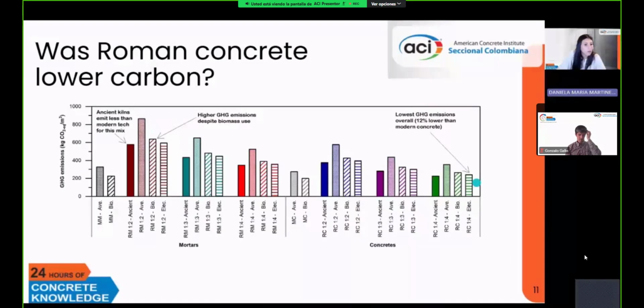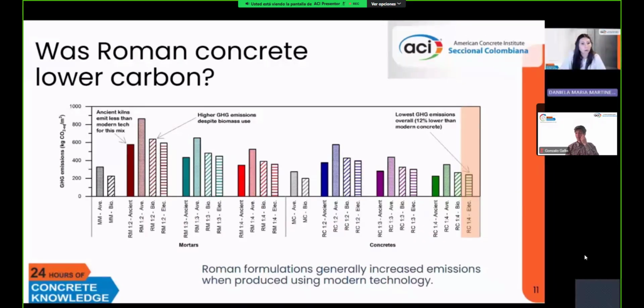We could see that there were some lower results compared to modern counterparts when we start looking into formulations that use more pozzolan, like this one that was a 1:4 ratio of lime to pozzolan, and also the production scenario meant that the calcination was completely done by an electric calciner using decarbonized electricity. The Roman formulations generally increase emissions when produced using modern technology, except for that final case.